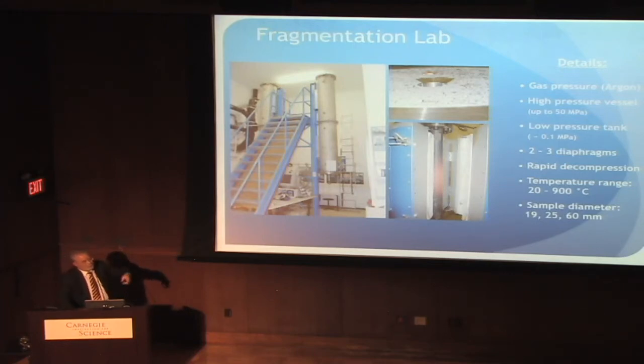We drill them out to a certain length and diameter. We pop them in an autoclave, a pressure vessel of a kind that was developed at the Geophysical Lab in the 1950s already, slightly modified by Tuttle and Bowen. And you see on the right-hand side, it's glowing red hot. This is the bomb, the autoclave, which is holding the sample before it explodes. How does it explode? We don't put dynamite in there. We don't shoot at it with a rifle, which has also been done by some of our colleagues in experimental volcanology. It wasn't particularly helpful for getting the field further in terms of acceptance.